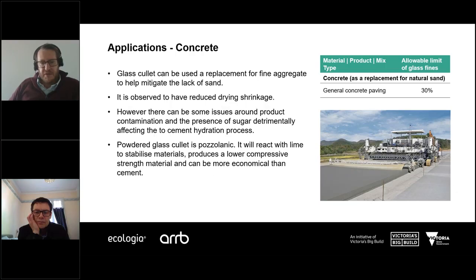Another note about recycled crushed glass is that if it's processed to a fine enough powder, it actually has some pozzolanic properties, which means that it can react with lime to stabilize materials. It would then produce a lower compressive strength material than using cement alone, which potentially has some advantages in some applications, and it can also be more economical to use than cement.